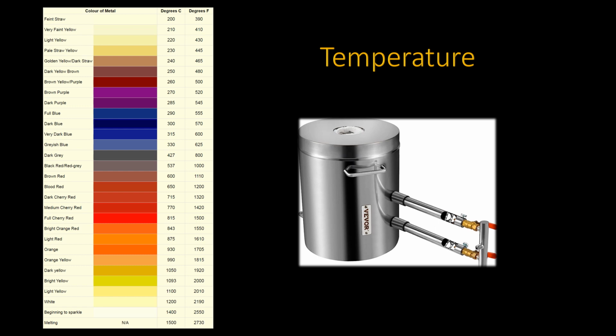Fulton states in his papers that the alloy must be between 800 and 850 degrees centigrade, and Mostowitz states that the lead oxide melts at 840 degrees C. But Bradford says that the lead oxide melts at 906 degrees centigrade. However, it passes through a pasty stage. The point is that the cupel must maintain a temperature above the melting point of lead oxide to be able to absorb the lead oxide.